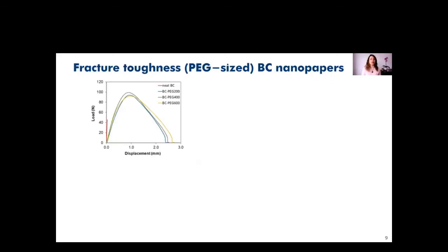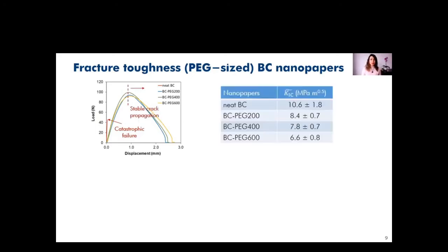So the second property was the fracture toughness of these BC nanopapers. The first curve we have is the load against displacement. The red curve for the neat BC shows that as soon as we reach the maximum load, the material fails in a catastrophic way. However, in the PEG-sized BC nanopapers, we can see that when we reach the maximum load, the crack propagates in a stable way. So the normalized K1C was measured, and the neat BC shows 10.6 megapascal per square root meter, and then the other materials have lower values.